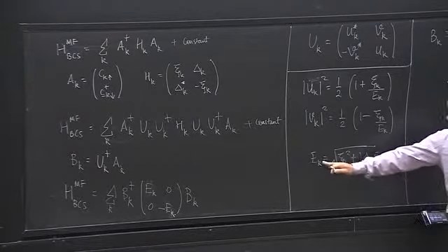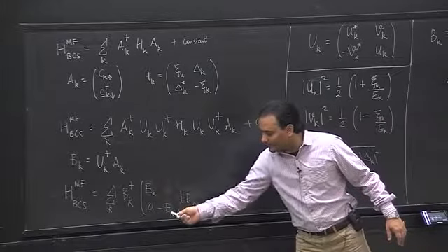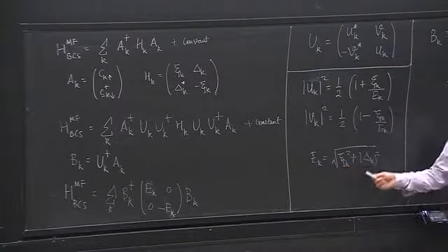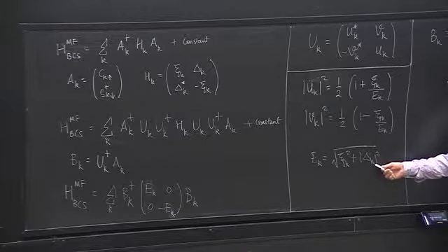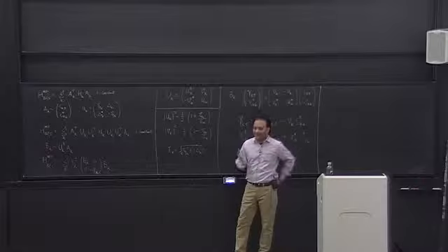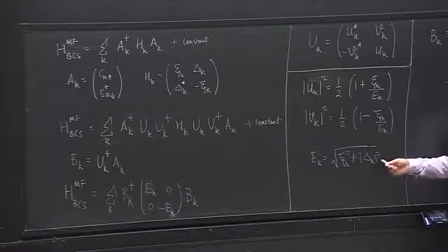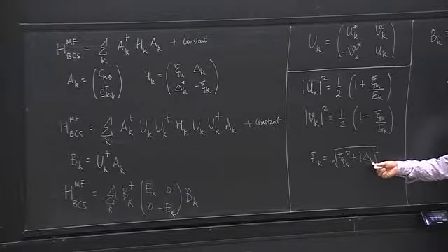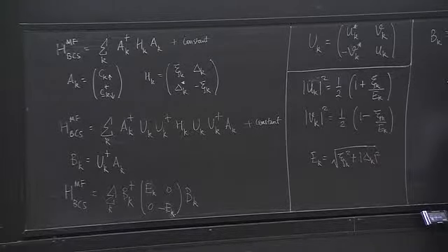In that case, the excitations, the diagonal values plus EK and minus EK, must have a gap. What that means is all positive energy eigenvalues are at least delta K. So delta K is like a gap. All excitations must be above delta K.